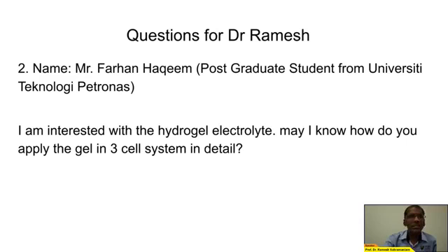When we talk about these things, the host polymer that we are going to use as a hydrogel also plays an important role, for example, polyvinyl alcohol. Why can we use polyvinyl alcohol as a hydrogel electrolyte? To interact with the ions, for example, in a lithium ion battery or lithium ion supercapacitor, the lithium ion needs to interact with the hydrogel. Polyvinyl alcohol can be used as a hydrogel because it contains the alcohol functional group, where there is an oxygen atom. This oxygen can interact with the lithium ion. That is why polyvinyl alcohol can be used as a hydrogel. And for this polyvinyl alcohol, we can use physical cross-linking or chemical cross-linking.